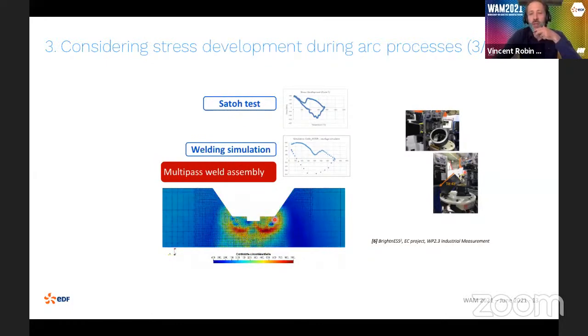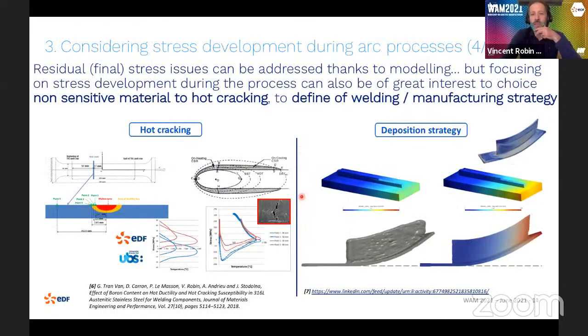Sandra Cabeza talked about this project yesterday, and the simulation was used to determine the most relevant position for neutron diffraction measurement on such industrial components. The second aspect concerns the fact that we are not only interested in residual stresses, but also in the stress developed during the process. And this is important information regarding hot cracking issues, for instance.